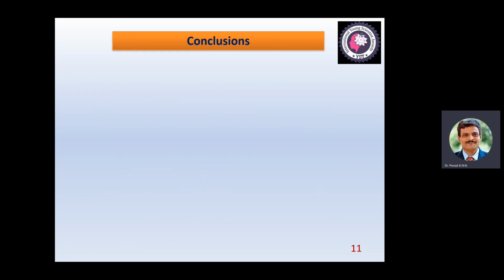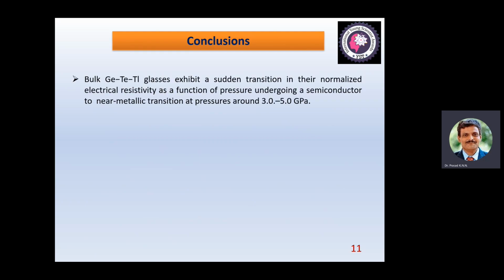Let me come to the conclusion part. The very first conclusion: bulk germanium, tellurium, thallium glasses exhibit a sudden transition in their normalized electrical resistivity as a function of pressure, undergoing a semiconductor to near metallic transition at pressures around 3 to 5 gigapascals. The second conclusion: the transition is reversible under the reversal of application of pressure, which is very important. So this application is going to be reversible in nature.